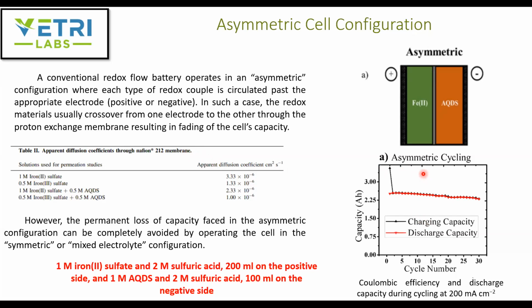So when they did the charge discharge capacity, where they recorded the discharge capacity by cycling at 200 milliampere per centimeter square, they saw that after the first few cycles, the capacity started to decrease, even before reaching 50 cycles. What you can notice from here is, with this system, there is a crossover. And how are they addressing the crossover? They're trying to use a different cell configuration, either a symmetric or a semi-symmetric configuration, which we'll see in the next slide.